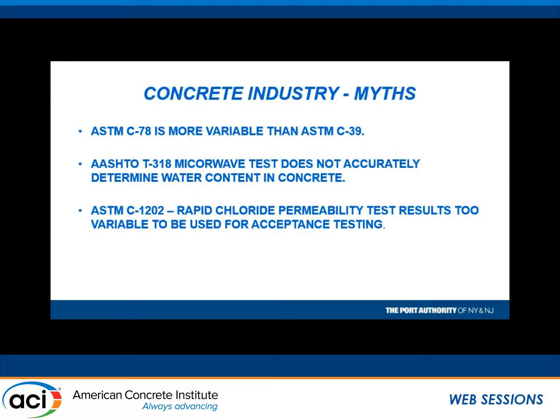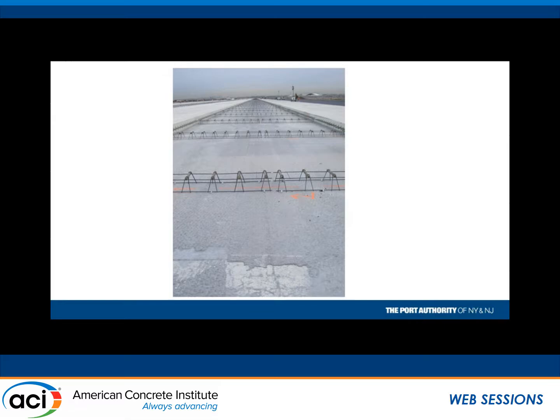There's a lot of good people here. Explain it to me how we do that. The rapid chloride permeability test. If we're looking at diffusion values, how do we not do that test when we're sampling for concrete for bridge decks? How do we just do compressive strength? Who cares? The compressive strength is not a big deal. I mean, if you can't get 5,000 PSI concrete, you might as well hang it up. You saw we got 8,200, and we were looking for 6,000. And that's not unusual for us to get numbers like that. If you control the water, control the air, the numbers go through the roof. Okay, that's our experience.